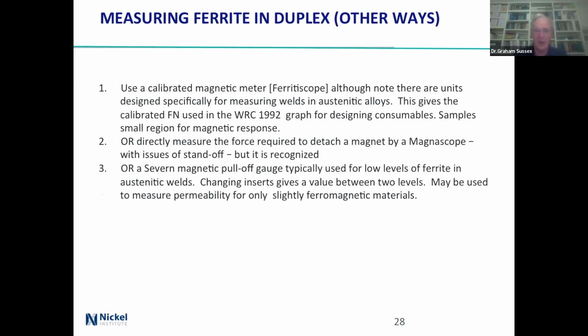You can measure it other ways. You can use a ferrite scope. I said that before. It'll give you units designed for welds in austenitic alloys, not in duplex alloys. There is a calibrated ferrite number used in the Welding Research Council 1992 graph for designing consumables, and it can sample quite small areas. The size of the sample is less than a centimetre. Or you can directly measure the force required to get a magnet off it with a Magnascope. There's a bit of an issue with standoff and shape of the surface, but still it is recognised, though not commonly used. Ferrite scopes are much more commonly used.